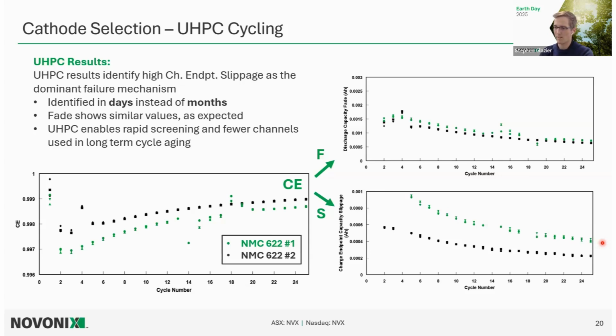electrolyte oxidation at the cathode, maybe a less stable cathode surface, or a coating that's not very effective at these conditions. Just cooking our electrolyte or a component of our electrolyte, and then after 8 months or 2,000 cycles, the impedance goes through the roof and our cell rolls over. But we can detect that just within a couple weeks, and even just in those first few cycles within days, using this UHPC cycling technique. So needless to say, this is what we do with every single one of our materials in order to enable really rapid development cycles and say, okay, this isn't working, let's try something new.